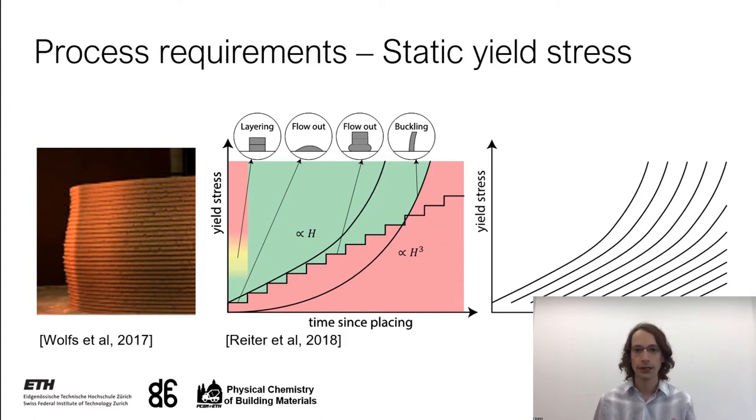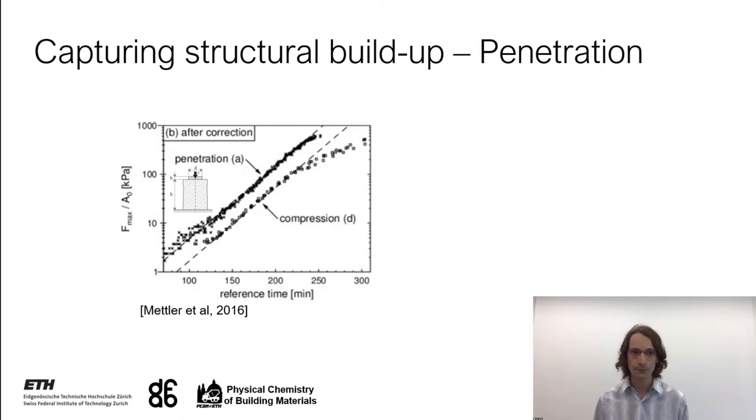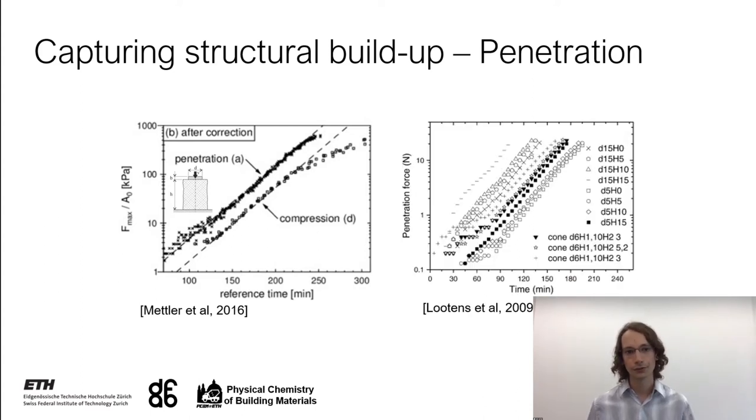And as we now know what we need, we of course need to be able to measure this so that we can fulfill it later. For this goal, penetration tests have shown to be very useful already before. Mettler and co-authors have shown that penetration and compressive strength scale excellently for mortars, and Lootens and co-authors have shown that in paste, there is an exponential increase of the penetration force over time.